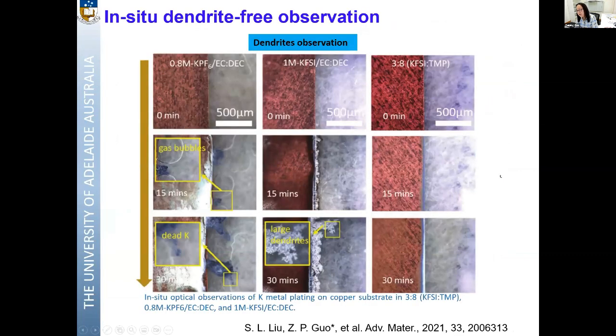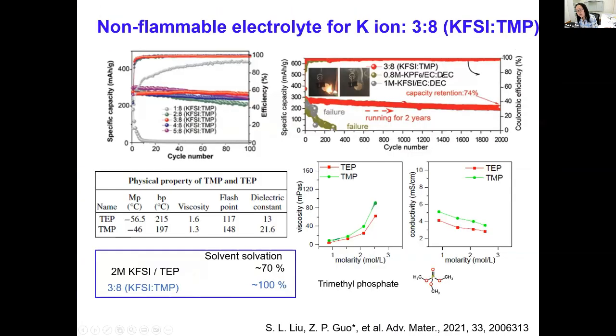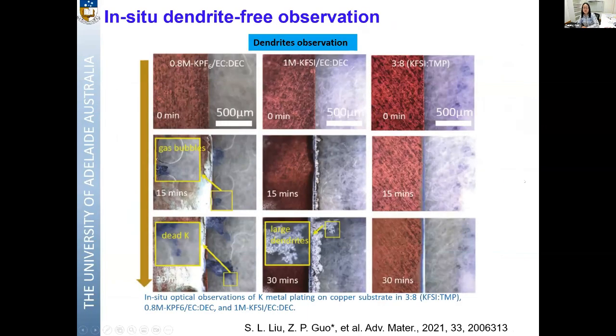And the cell, by using this TMP-based electrolyte, can be discharged for 2,000 cycles, more than 2 years, with capacity retention still about 74%. And from the in situ optical microscope, we found this electrolyte can achieve dendrite-free potassium deposition. You can see after continuous 30 minutes of potassium plating stripping, we cannot observe any dendrite formation. While in the carbonate-based electrolyte, we can clearly see some gas bubbles appear, large dendrites, and also dead potassium accumulate on the surface.